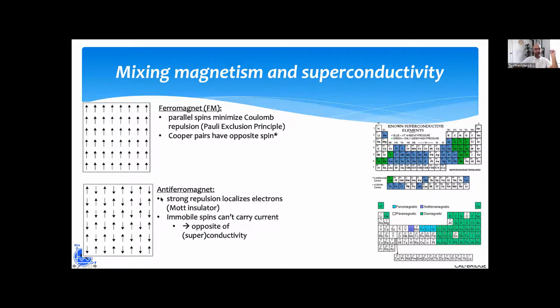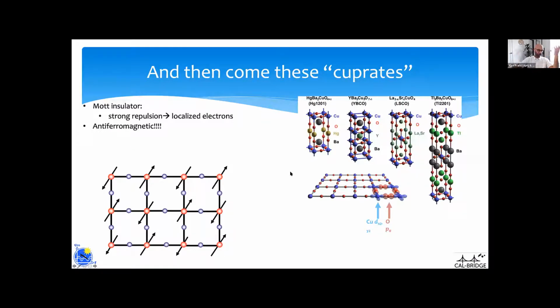There's also antiferromagnetism, where you have electronic spins pointing in opposite directions. But the bottom line is that these copper oxides that we also call cuprates turn out to be antiferromagnetic. So the spins are very much aligned, it just happens to be anti-parallel. But this here, in theory, should be the worst enemy for superconductivity.